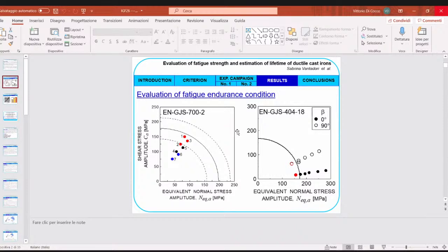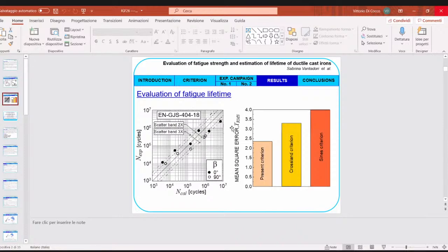It has been shown that with the multi-axial criterion employed, a quite satisfactory accuracy in the evaluation of fatigue endurance condition has been achieved. Moreover, for finite fatigue life tests, the number of loading cycles to failure has been estimated with a satisfactory accuracy, far greater than that related to other multi-axial criteria available in the literature. Okay, thank you for your kind attention.